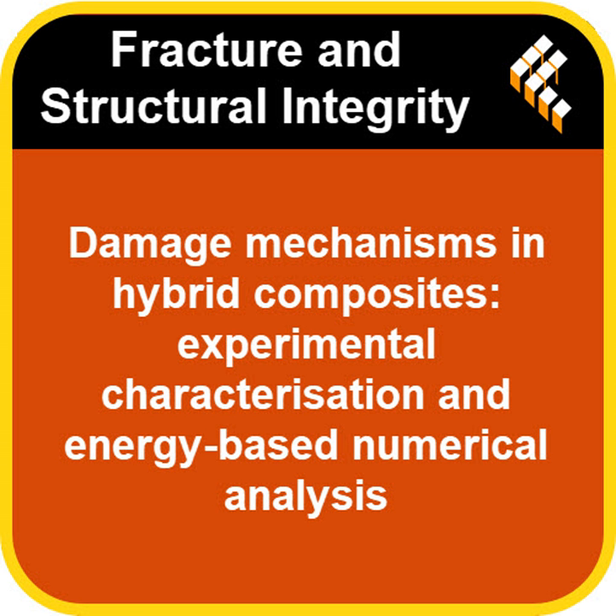Definitely. The force and bending amounts that the models spat out were generally within the typical variations, the standard deviations they saw in their physical tests. So the predictions were pretty solid. Were there any noticeable differences between the real and virtual tests? They did note a couple of things. The computer models sometimes predicted a slightly higher maximum force than what they measured experimentally. Okay, a slight overestimation. Yeah, just a bit.